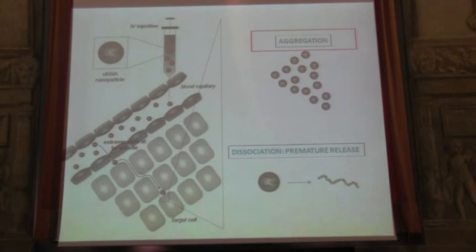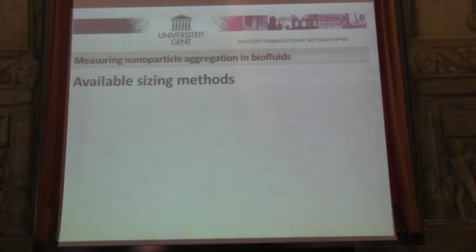Because typically nanoformulations have a nominal size of, let's say, 100 nanometer. And considering the fact that the fenestrae in the blood circulation, in the capillaries, are typically between 100 and 400 nanometer in size, you can imagine that even the slightest aggregation of these 100 nanometer particles already alters the biodistribution indeed. So we would like to do sizing to measure aggregation of nanoparticles in the blood circulation.